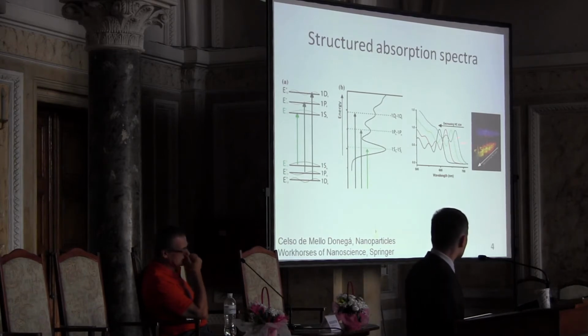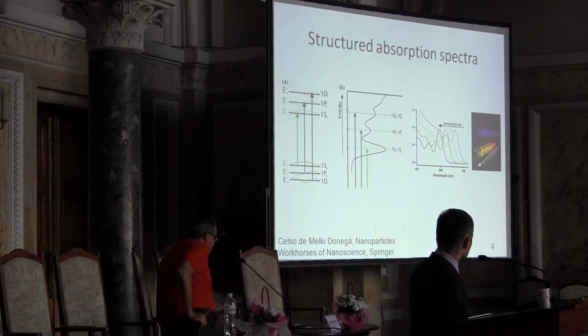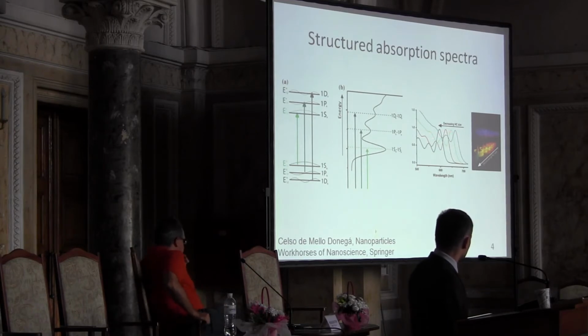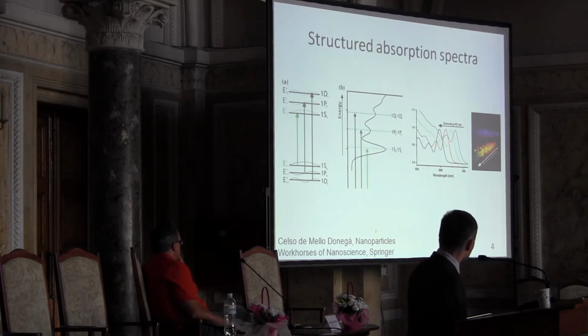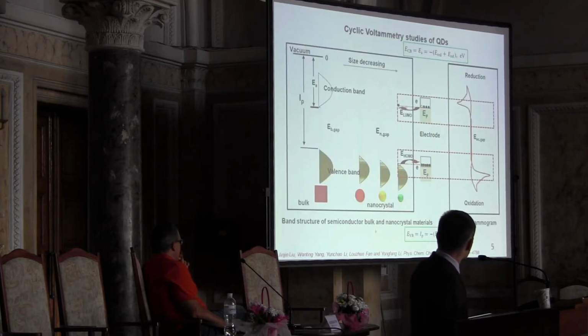Like you can see here, these are different sizes of quantum dots, becoming smaller, for cadmium selenide. It also means a shift of the absorption maximum, which corresponds to the first and further excitonic transitions, to shorter wavelengths, basically. And of course, you can probe those shifts with different methods.